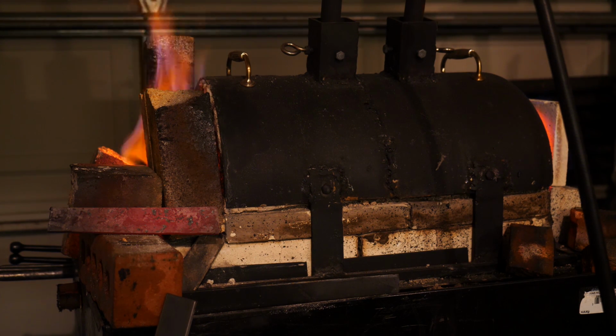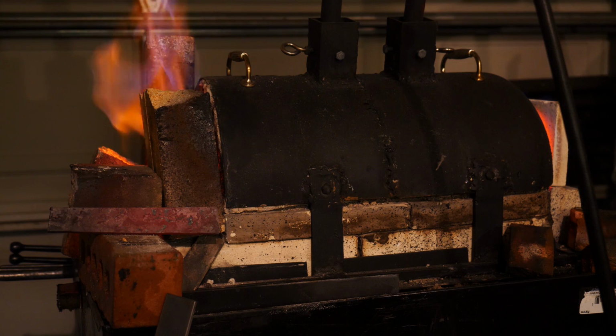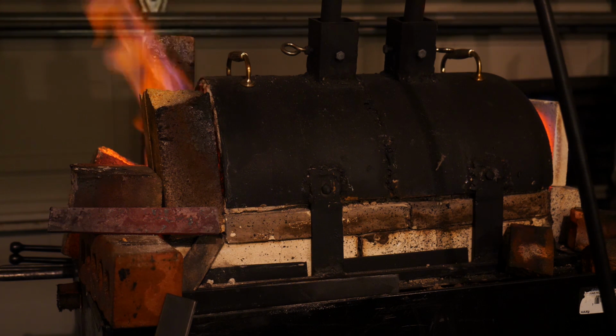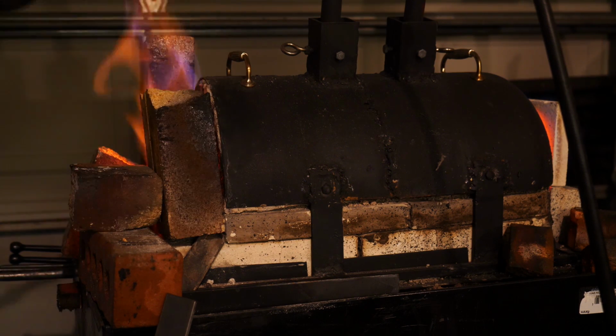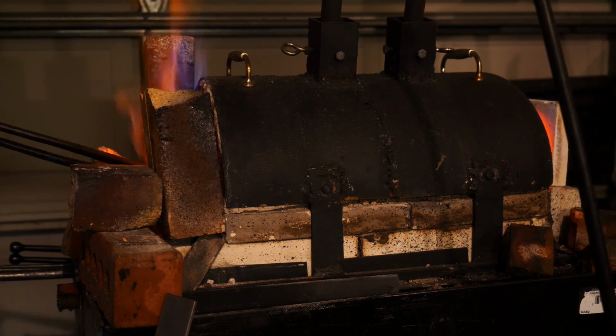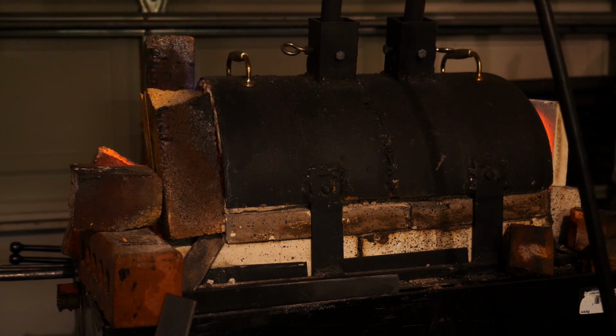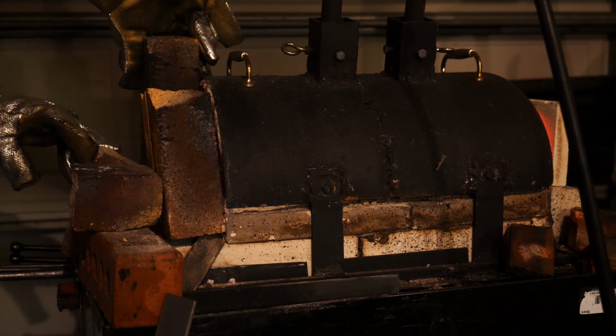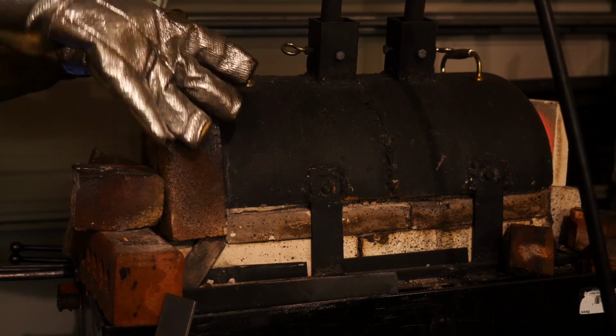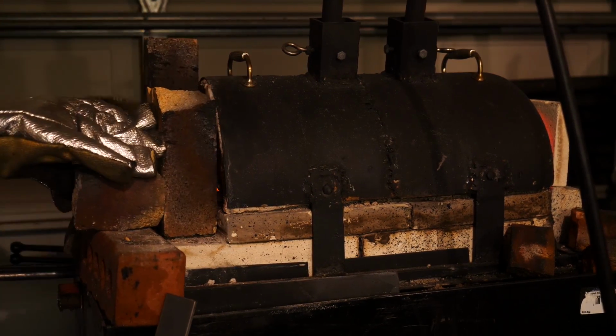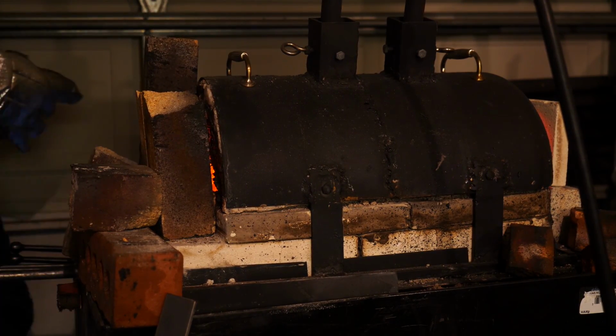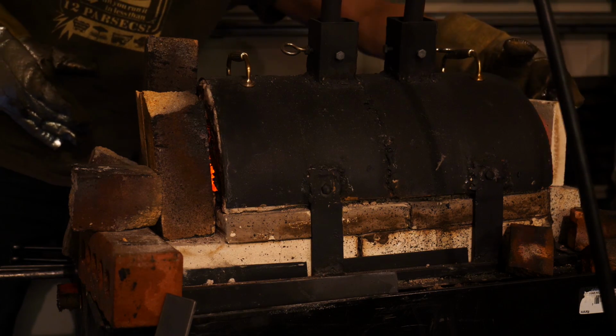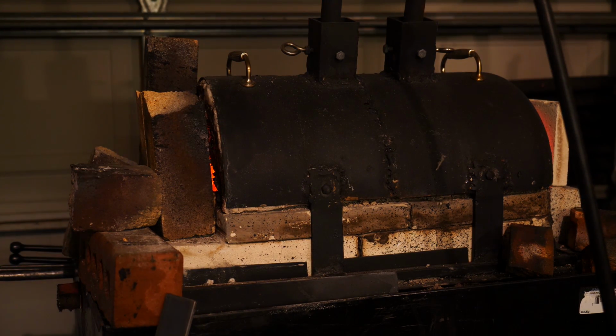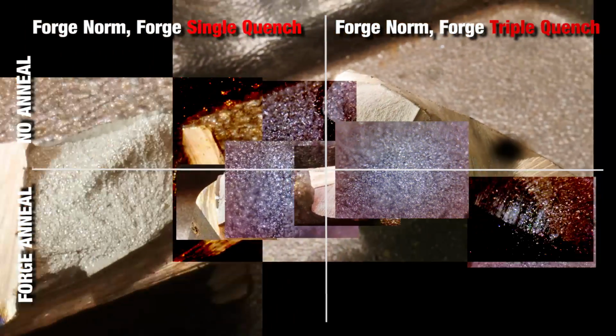You can do sort of this rough and tumble forgeside anneal by getting it to non-magnetic, taking it out of the forge, letting it cool to a gray, then putting it back in the forge, turning off the forge, and then just letting it cool. This took about 8.5 hours to get to room temperature. So from a time standpoint, that's a pretty decent anneal cycle, but I wouldn't say that this is adequately annealing 5160 to its true potential, but let's just see what happens.